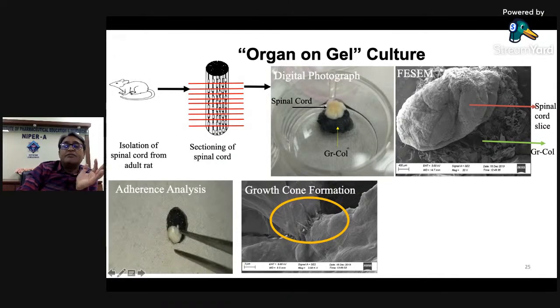Then we were further interested in how much attachment it has done and why it is so attached onto the material. For that, we did scanning electron microscopy, and we found there's a formation of some growth cones between the tissue and the material. This means the cells present in the tissue are trying to attach to the material. These growth cone formations were observed.